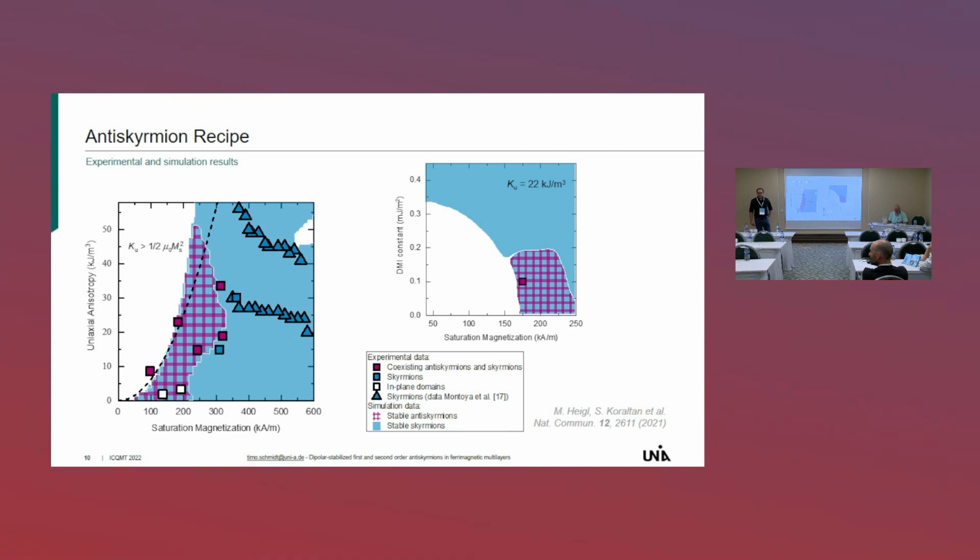Also, I remember Eric Fullerton was telling me that in that system they saw a 3D structure. In the middle there's a Bloch skyrmion, and then there are Néel caps on top and bottom. Do you see any depth-dependent variations of the spin texture? Could you explain it a little bit? Their system is without this iridium, just iron gadolinium, and typically you see the Bloch skyrmion, but at the top and the bottom there's a different configuration.